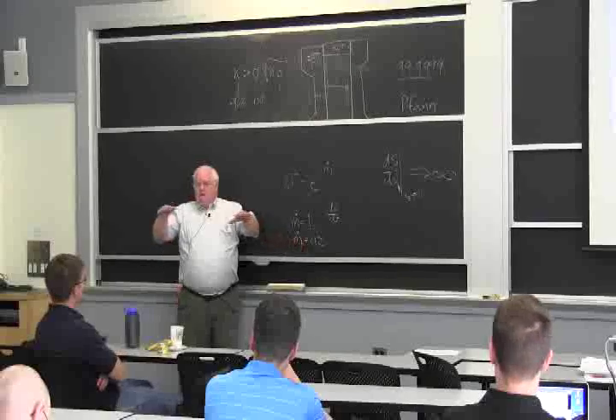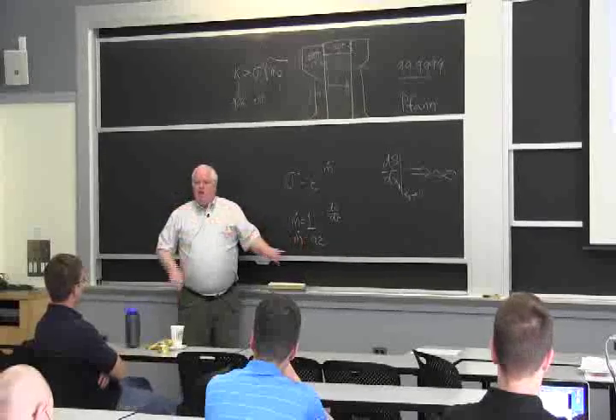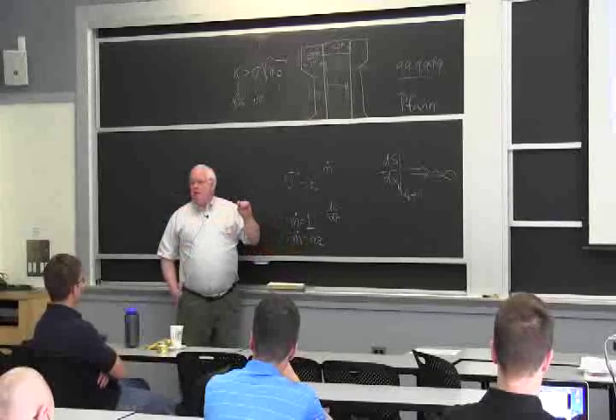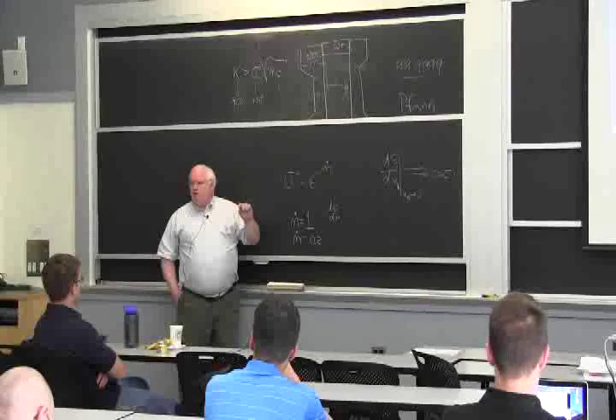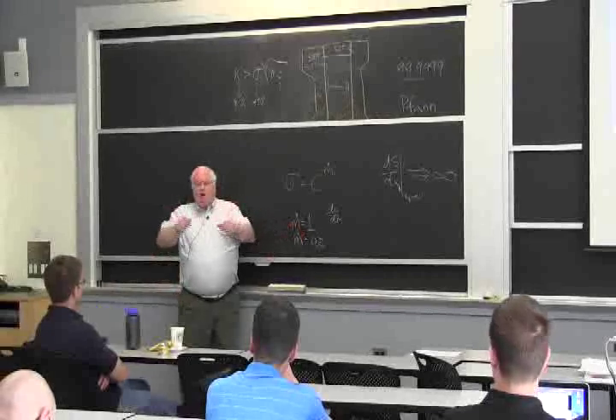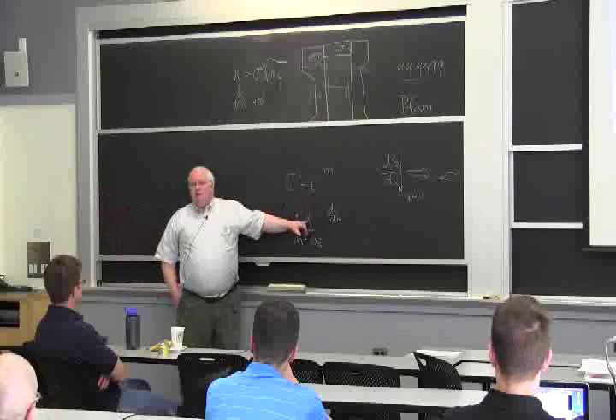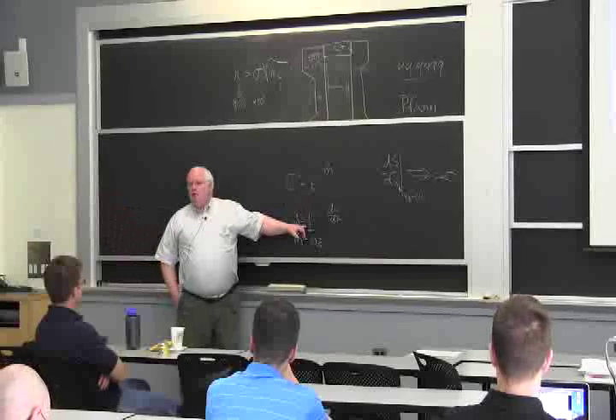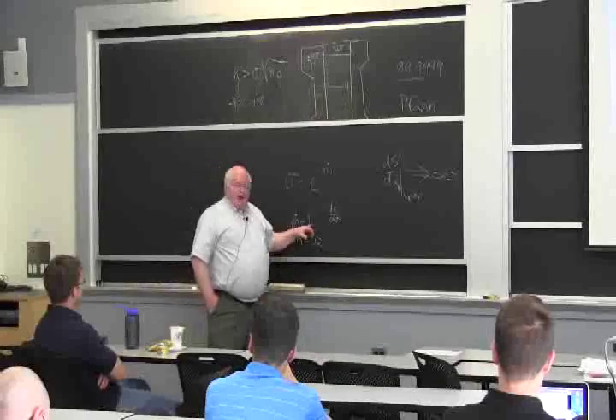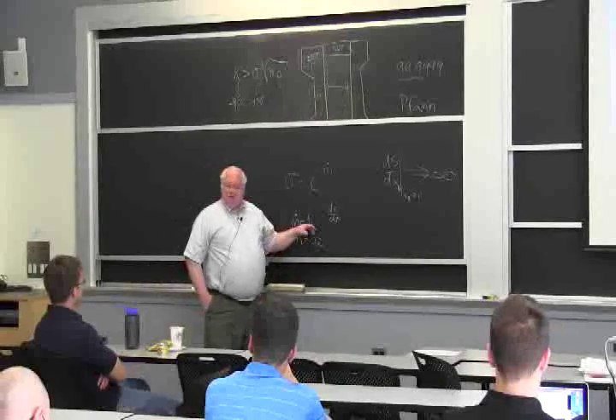So if you have any instability in a metal where it starts to thin down a little bit, that instability will grow, it will neck down and break at the thin spot, or the small diameter instability. A Newtonian metal, you can have a little neck in there, and you can pull it out 100 miles if it really is an M of 1. Now, the only Newtonian fluid that we might work with typically is glass. Glass may have 0.9. Metals typically have 0.2.